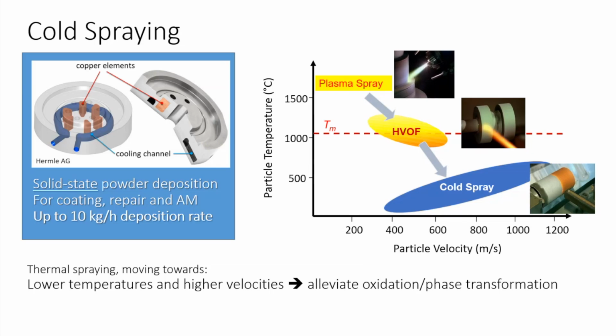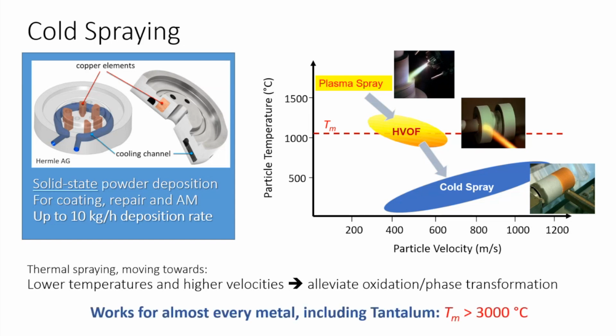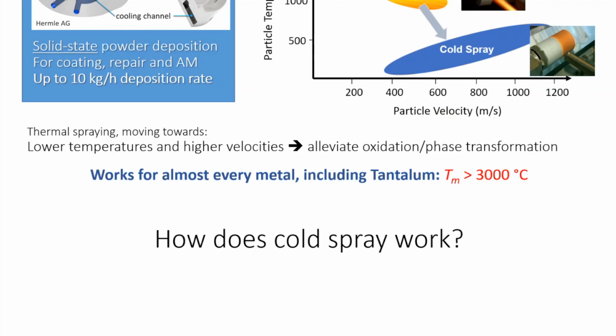Interestingly, you can use cold spray to deposit refractory materials, including tantalum, with a very high melting point, which you would have trouble with if you wanted to use conventional thermal spraying methods. Based on that, a main persistent question in cold spray research has always been, how does it work? What's the mechanism behind that? I would say it's still maybe an open question. I would try to shed light on that a bit through the exposure to cold spray research. But I'm not going to give you probably the best answer to this question that we know so far.